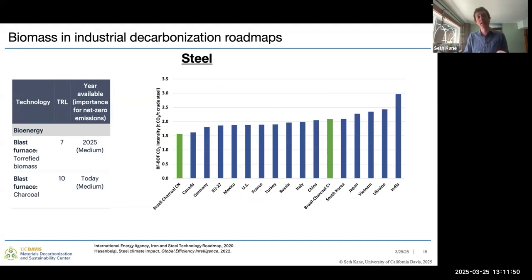We also, in steel, it is a little bit different, primarily because we're already doing this a little bit, mostly in Brazil. So I've highlighted in green there. This is a figure from the IEA showing 2 different ways of accounting for the emissions of Brazil's steel production. The one on the left is if you account for the use of bio-based carbon as entirely negative, and you can see in that case, they have some of the lowest emissions of any country for steel production. And that's because they're using about 10 million tons of bio-based carbon in place of fossil fuel derived coke coal. However, they're not always using residues for that. And when you account for those agricultural emissions, that does go up a bit, which is what's shown in the green bar on the right there.